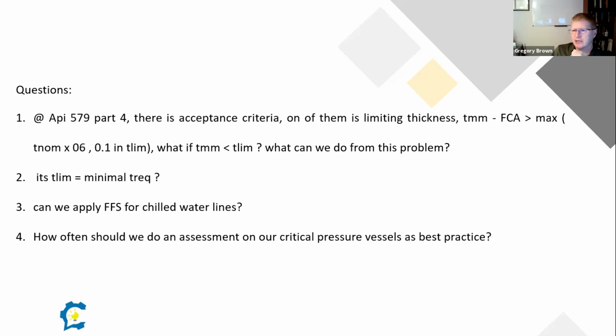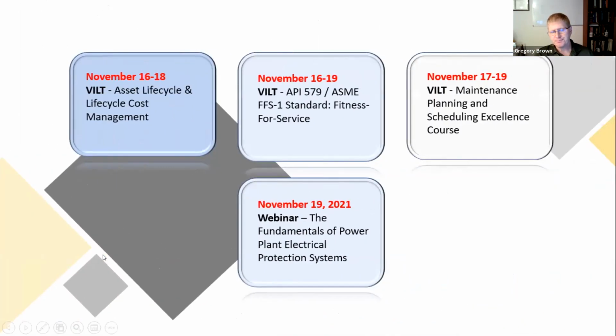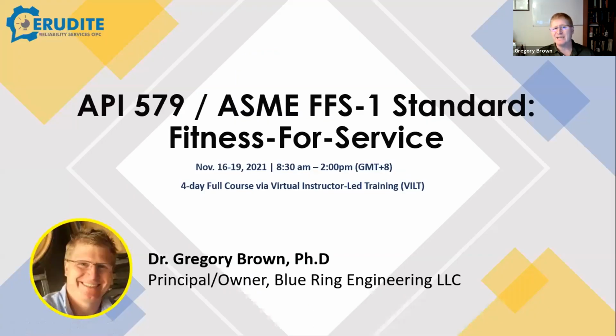Then in that case, you're not going to be able to compare. If you're really at that limiting thickness, that 2.5 millimeters, 1/10 of an inch, you're not going to pass the level 2 assessment, or you pass it today, but when you do the assessment you always need to include a future corrosion allowance as well. So if you're right at the limit, when you apply any future corrosion allowance, obviously you will not satisfy that level 2 assessment. It is possible that a level 3 assessment would help you, but that can be challenging because you need to justify why you could operate a location with very, very thin wall.